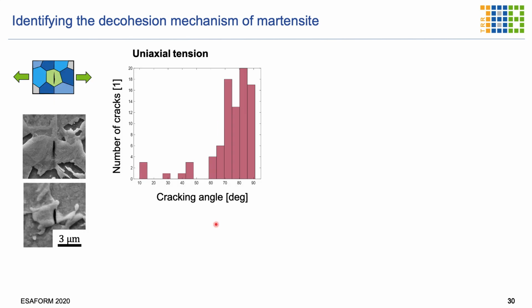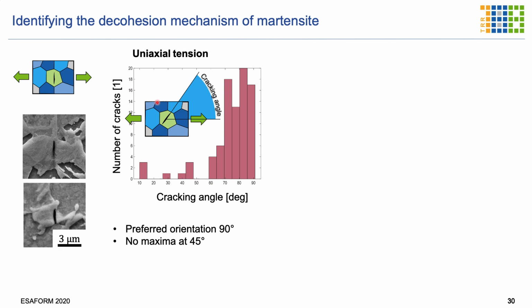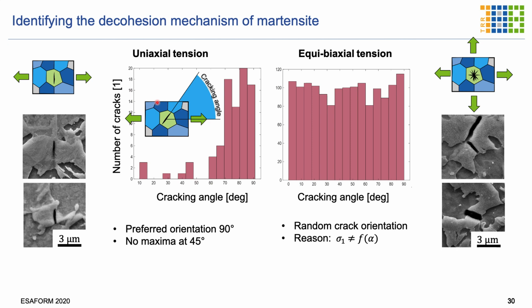So what we did was we analyzed those modes under the microscope and found that during the uniaxial loading, this mode 1 direction, which corresponds to 90 degrees, this is the cracking angle, is the basic mode which we have in the cracking of the martensite. Oh, sorry, here is the angle once more shown. And that is the preferred orientation for cracking in uniaxial tension, the 90-degree mode. If you look at equi-biaxial tension, the situation changes. Then any angle, any orientation can be a cracking orientation. So that's very important, that we have to identify those mechanisms in order to use them in our models.